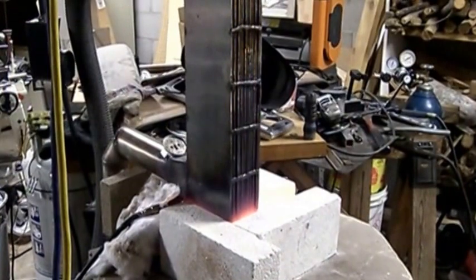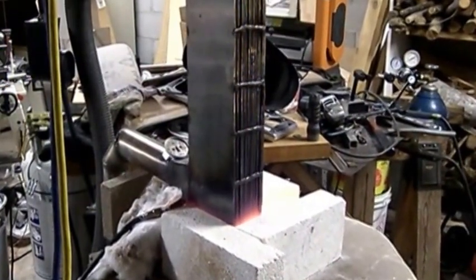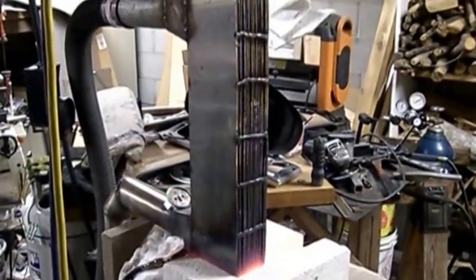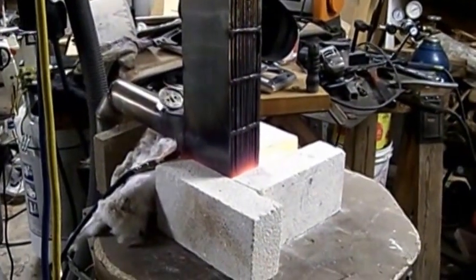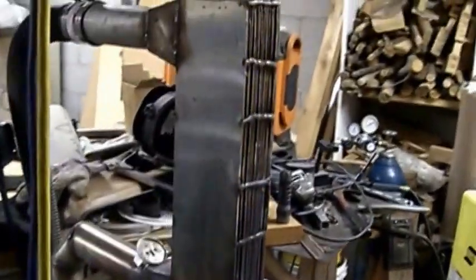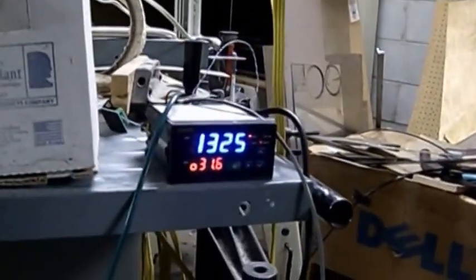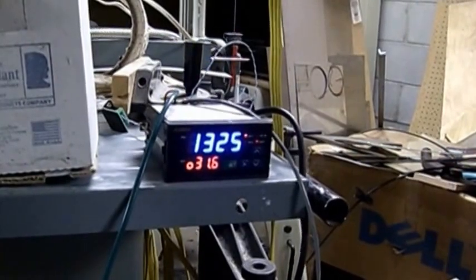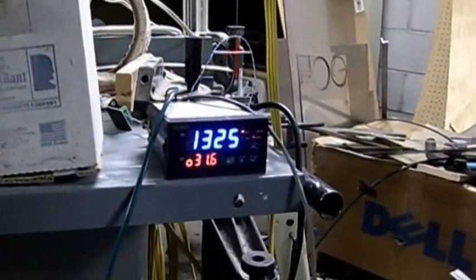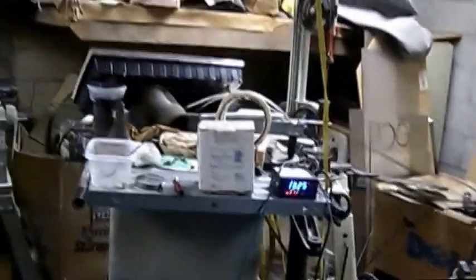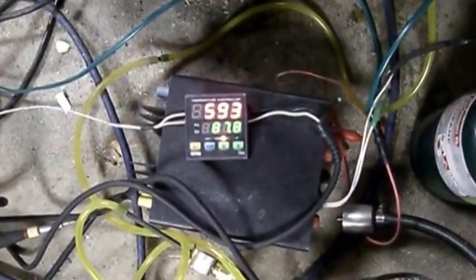Alright, we're almost at the end of the firing here. It's so stable, using hardly any fuel, which is really impressive. So we were using 35 or 36 before. Almost at the end, 31.6. So we're very efficient here. It's very good. We're maintaining our preheat temperature right around 600. Everything's looking good. Hopefully all my pieces turn out.